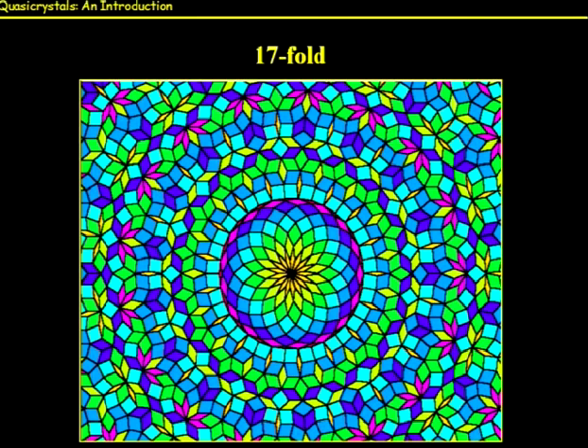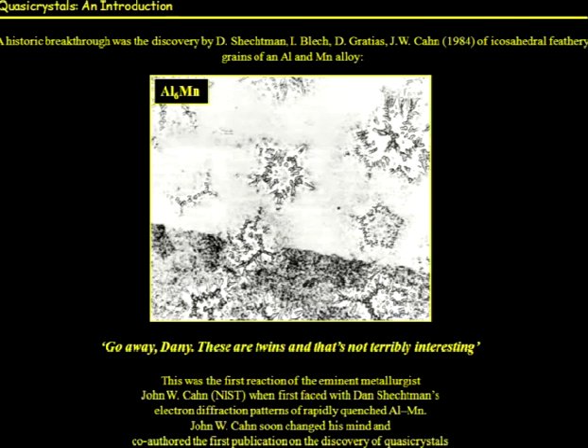As it happens, again in 1984, Dan Shechtman, Ilan Blech, Denis Gratias, and John Cahn, working on rapidly cooled icosahedral grains of aluminum-manganese, found experimental evidence. So you can see here this very remarkable diffraction pattern. You can see here the 5-fold symmetry, okay, in this place. Well, Dan was a visiting professor at NIST in Washington in that period, and he obtained this experimental image 2 years before, in 1982. He was there under the supervision of the eminent U.S. metallurgist John Cahn.